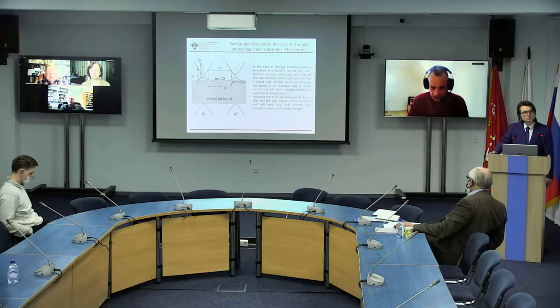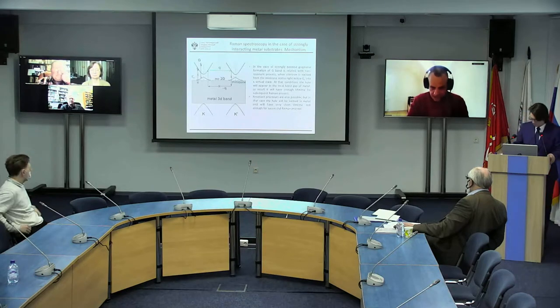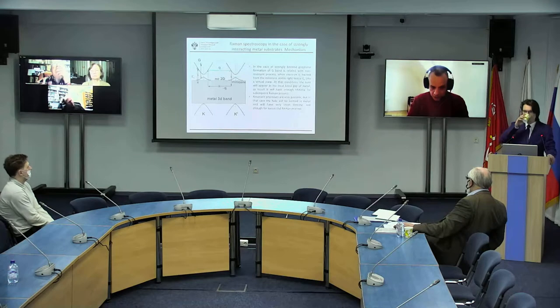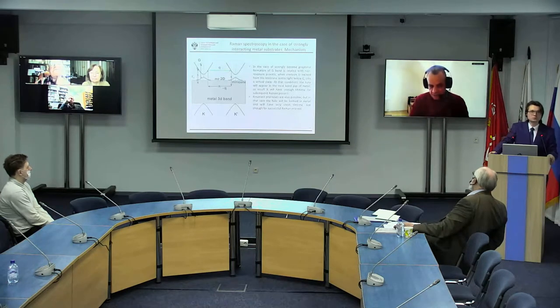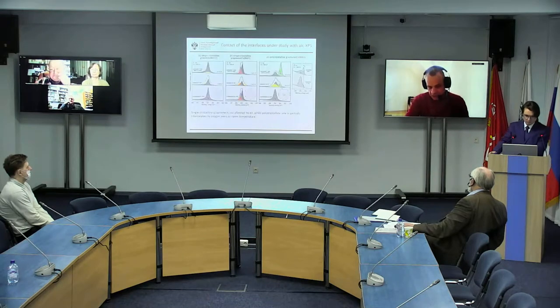Then what he found in chapter number 3 is that in the case of monocrystalline graphene on cobalt, one point is he always measures these samples in air. So he sees a G-band, but as far as I understood, he does not see a 2D band, and he does not see a D-band. The D-band, one might argue, is because of the lack of defects, and for the absence of the 2D band, he has developed a model.